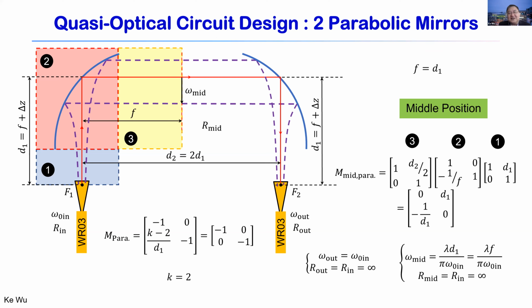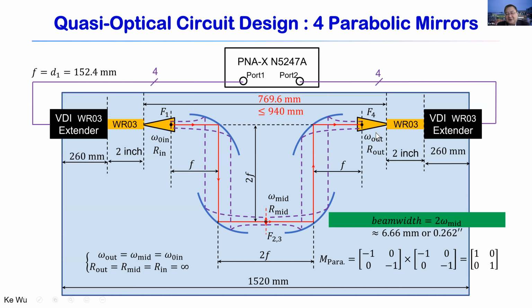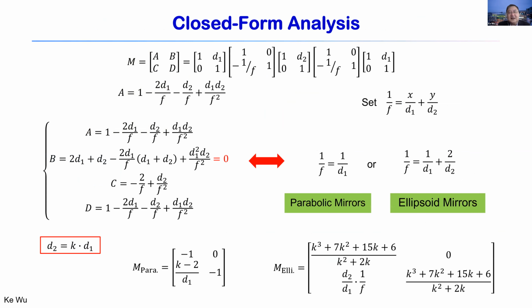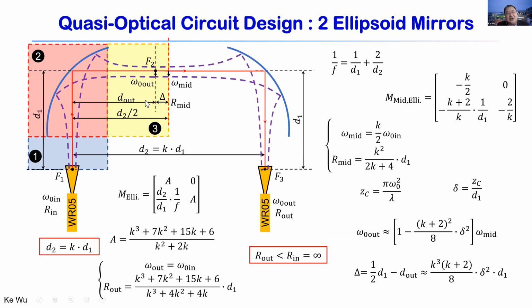But on the other hand, the elliptical measurements, let me go back to this. You can see that you can create a very fine beam here. This very fine beam can be used for specific spot measurements. For example, if you have a thin film which you want to test, the thin film will have uniformity over the entire structure. In this case, what you want to do is the so-called imaging. Let's say you make your thin film move around here, you're able to see the uniformity of the film through the measurements. At the same time you can create imaging. So the quasi-optical based ellipsoidal mirror system can be used to create an imaging system. This is very convenient here.